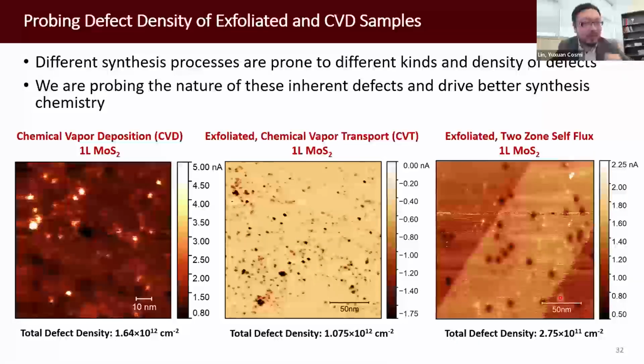So the sample preparation is not that straightforward. We struggle a lot with the cleanliness of the sample, but eventually we can demonstrate good imaging for different samples. This is a CVD monolayer MoS2. We can also exfoliate monolayers from a crystal grown by chemical vapor transport. And we also demonstrated an exfoliated sample from the two-zone self-flux method.